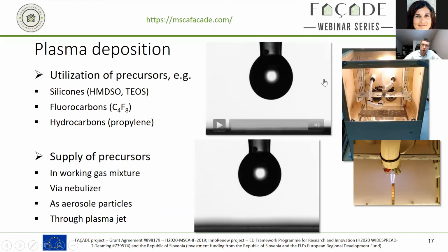One particular example on the right-hand side is a small system that we have in the lab with a mobile digestorium to protect from any aerosols that come out of these plasma treatments due to the conversion of the precursors. This can be used in such a way that it's producing, from silicone-based precursors, either hydrophilic or hydrophobic surfaces.